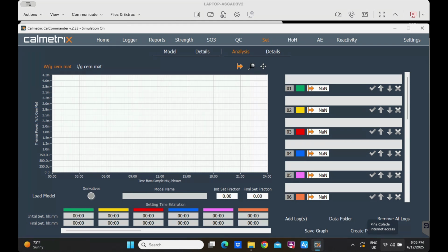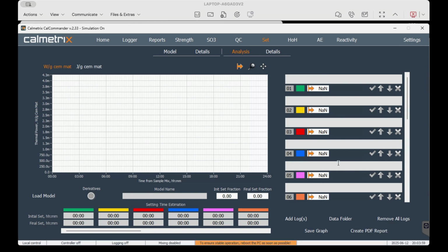Alexander is asking, it's a long question here. So with adiabatic, developing a method for set times and using Thermocal 2, we have been instructed that a good general rule of thumb for the initial and final set fraction is 1/3, 2/3, or refer to ASTM C1753, which cites values 0.21, 0.42. Is this the rule? So yeah, Alexander, the rule is still applicable whether it's semi-adiabatic or isothermal.